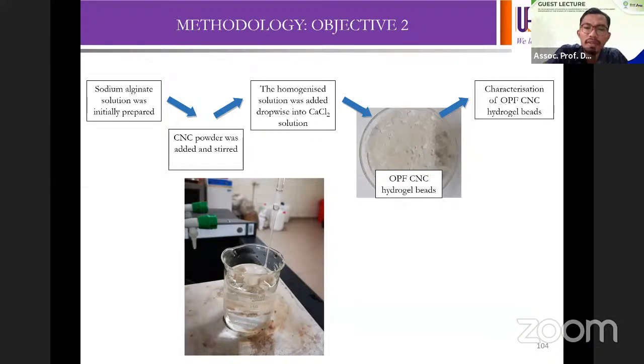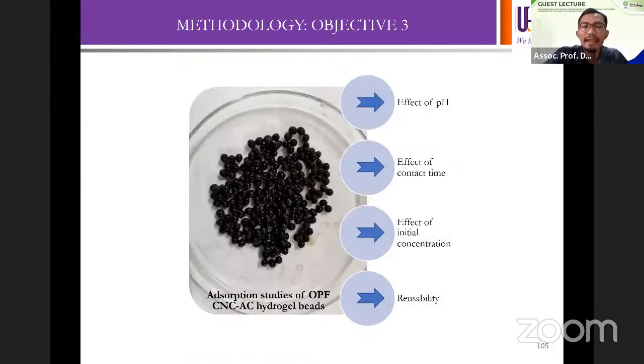Why we form a bead is because for the adsorption studies, we want to make sure that after the adsorption process, we can easily isolate the adsorbent rather than in powder, for example. And to make it more interesting, we also include activated carbon to the bead. So it will be a composite adsorbent. You will have cellulose nano and also activated carbon that can actually improve the adsorption and the removal of wastewaters.